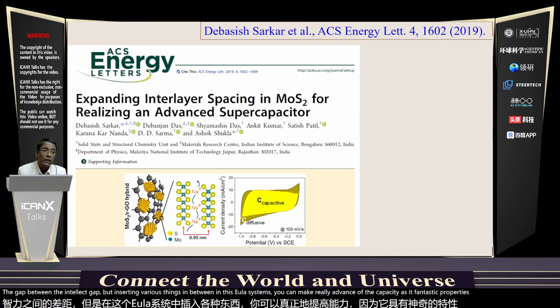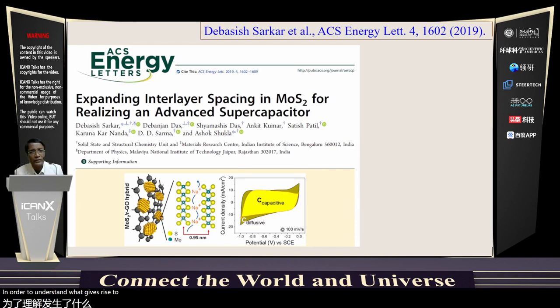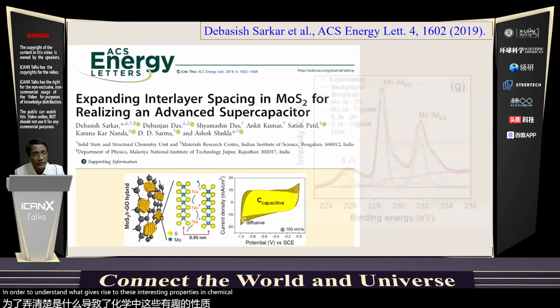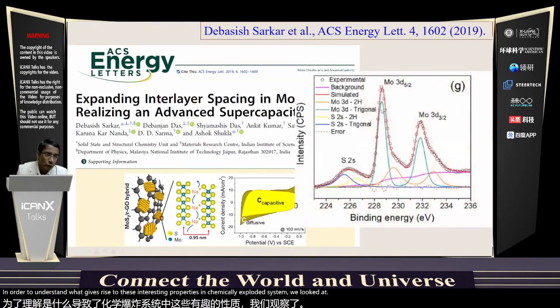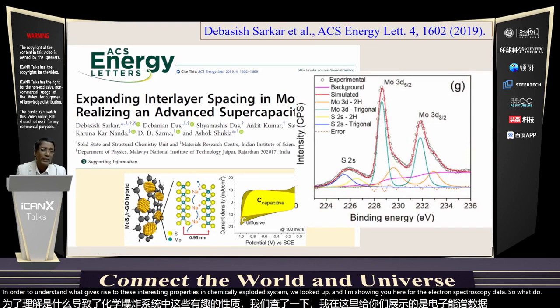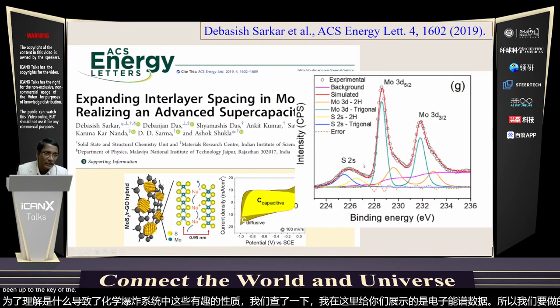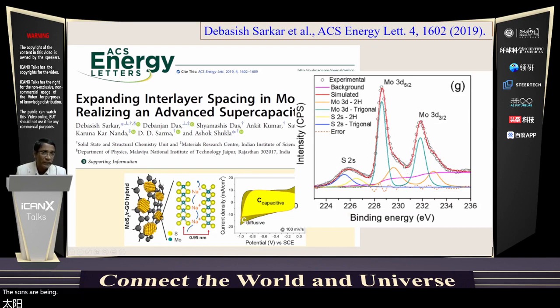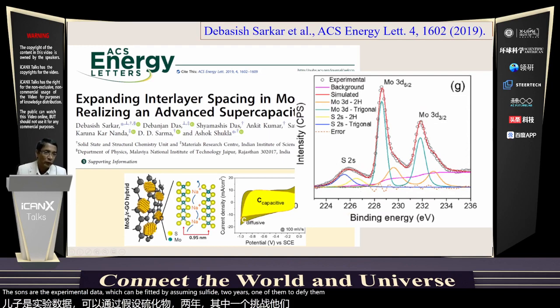In order to understand what gives rise to these interesting properties in the chemically exfoliated system, we looked at, and I'm showing you here, photoelectron spectroscopic data. What we are doing is looking at the core level of molybdenum 3d5, molybdenum 3d3, this peak, and this bump here is coming from the sulfur 2s signal. The circles are the experimental data, which can be fitted by assuming sulfur 2s, molybdenum 3d5, and molybdenum 3d3.